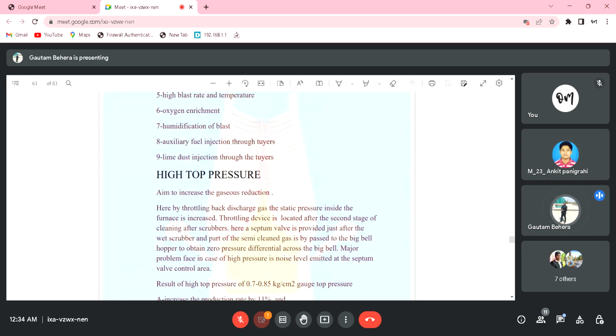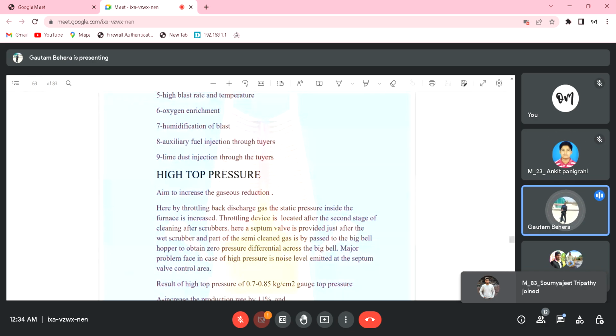Can you please be louder? Sir, ash content will be more, so the volume of slag will increase. Right, very good. Because we are injecting pulverized coal, that is actually a coal. Coal means more ash content. More ash content means more volume of slag, obviously. Very good. And what happens to the silicon content and sulfur content of the hot metal?